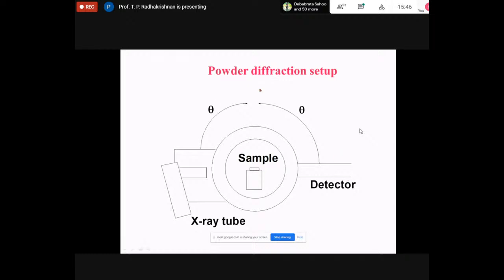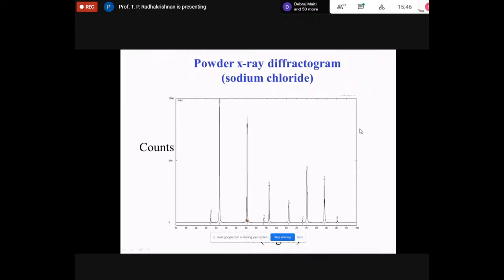There is a detector here, which again can be rotated. So the X-ray scattering will be detected by a detector at different angles, and it will plot that data. Here it basically looks at this data. At different angles, there is an intensity of scattered X-ray coming out. So this is the famous diffraction pattern of sodium chloride.